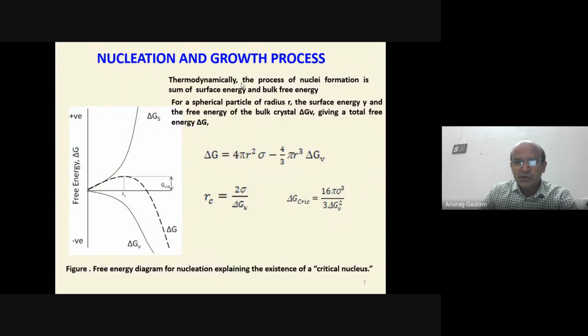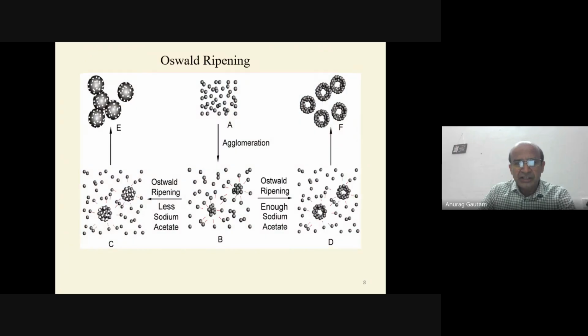Now this is also how they grow, right? This is nucleation and growth of a particle. For any particle to grow, it must reach the critical radius, RC. If they are below that, they will dissolve. So there is a critical radius. Above that it is very important, because at the critical radius, delta G, the energy required to grow, is reached. And if the radius is below RC, they will redissolve. This is a well described, old theory of how particles grow. Initially, a bigger particle takes the smaller ones on its surface. That is called the Ostwald ripening process, and it is the way of increasing particle size.